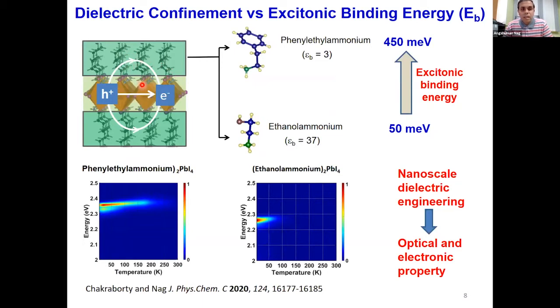To give an example of this, let me show here. This is the layered perovskite structure where we have changed the organic layer. The inorganic layer remained constant, and the organic layer is, for example, here phenylethyl ammonium. Then you get a small dielectric constant for the barrier layer, that is 3. And for that, you get a very high excitonic binding energy. The excitonic binding energy is about 450 meV.